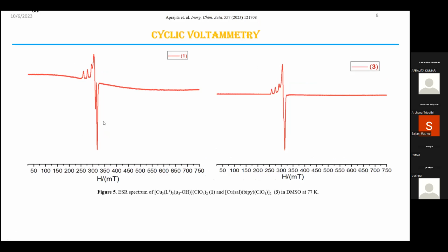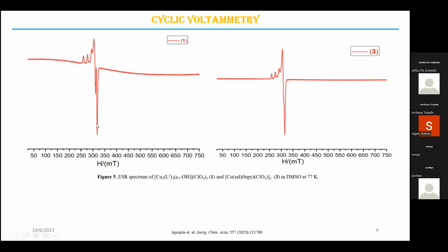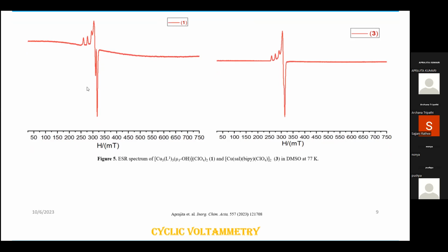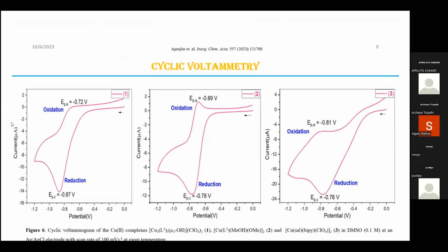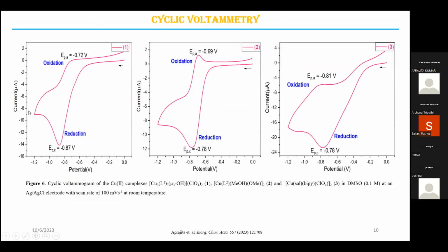Here we have taken the ESR spectrum of copper complexes 1 and 3 to show their polynuclear character. The ESR spectra show the characteristic of an axial spectrum with well-defined four hyperfine lines in the parallel region, due to the interaction of the electronic spin with the nuclear spin of the copper center, suggesting polynuclear complexes. Through cyclic voltammetric analysis, we studied the electrochemical properties, and each of the complexes shows a peak in the forward and backward direction, showing the redox properties of the complexes.